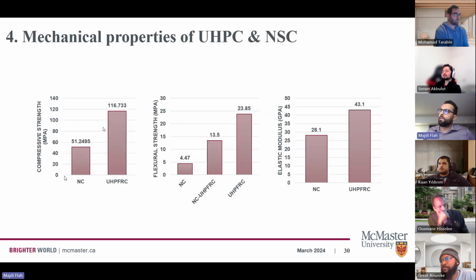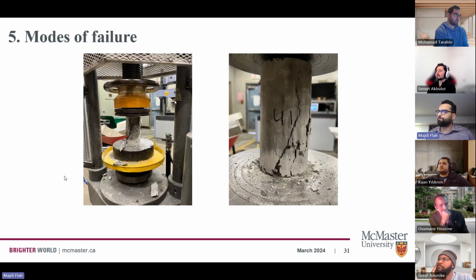And talking about the mechanical properties now of UHPC. As Great mentioned in the beginning, we had almost 117, I would say, MPa compressive strength, which wasn't expected because we were expecting more than 120. But given the size of the silica fume we got, it looks like that's reasonable. For the flexural strength, a very big increase, almost 5 times that of normal concrete for the UHPC. And for the elastic modulus, there is also a good increase from 28 to 43.1 gigapascal.